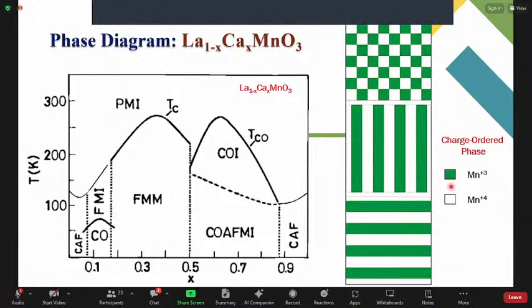This is the general phase diagram shown by such kind of LCMO manganite. So here for my study, I have used La0.3 and Ca0.7. So if we go for x equal to 0.7, we can see that around 250 Kelvin, we will get a transition of charge ordering. So at room temperature, my sample will be a paramagnetic insulator. Now around 250, it should show a transition to the charge order state, and below that again it should go towards the AFM, meaning antiferromagnetic transition.